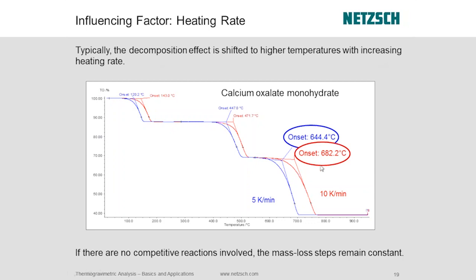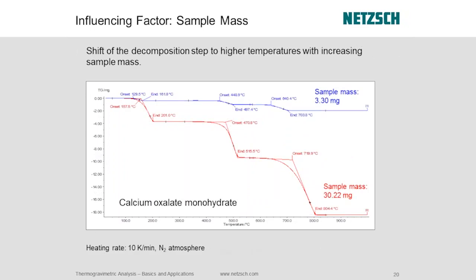So we talked about gases, we talked about heating rate, and now let's talk about sample mass, all right? If we increase sample mass, a rule of thumb is that we get a shift in the decomposition step to higher temperatures with increasing sample mass. So similar to what we just saw with the heating rate, you get a shift. Here's a mass of 3 milligrams versus a factor of 10 more, 30 milligrams. Okay? So we're getting a shift again to higher temperatures with increasing sample mass.